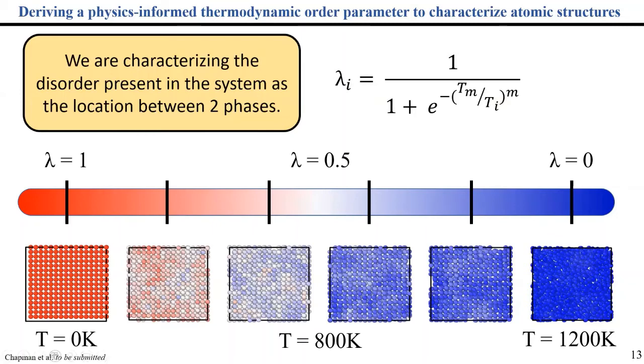What this actually does, though, is that an order parameter of 1 is the perfect ideal 0 Kelvin crystal. An order parameter of 0 is a pure liquid phase at the melting temperature. And everything in between is some mix of those two, based on what the graph neural network learned as you provided it these snapshots during training. So really, the order parameter value itself is a kind of distance in space between these two phases of the material. And in this case, everything is going to be shown for just FCC aluminum as a case study.